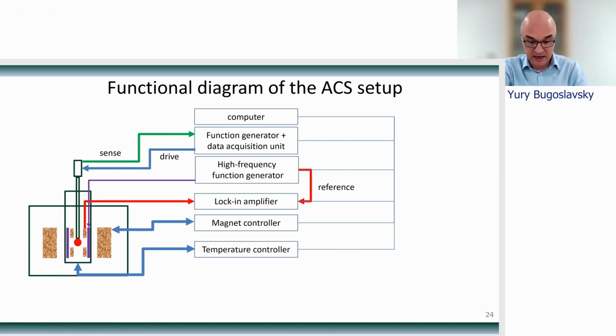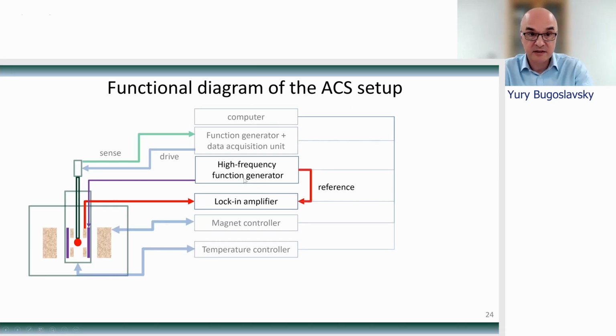To make the VSM work as an AC susceptometer, we need to make a few additions to our electronic stack. We need to add a high frequency function generator, which is connected to a small solenoid generating a high frequency field. The coil is still connected to the lock-in amplifier, but now because we are measuring at the frequency of the AC field, the reference signal is taken from the TTL output of the high frequency generator. The rest of the system remains essentially the same.